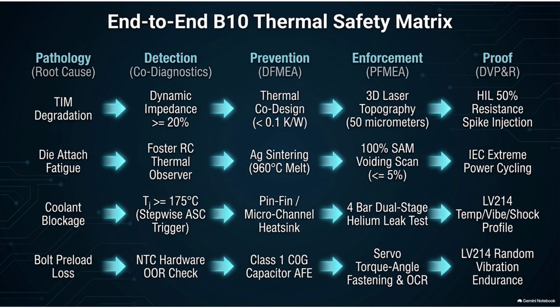It proves the physical architecture can withstand reality. It verifies that those tiny aluminum pin fins inside the cooler don't develop fatigue cracks and snap off under intense vibration. It proves the thermal paste doesn't wash out or pump out when the metal is shaking and warping. And the sensors? It ensures the delicate NTC temperature sensor's accuracy doesn't drift more than 1 degree Celsius, despite being violently shaken and frozen. And crucially, it guarantees the electrical insulation resistance remains rock solid above 100 megaohms, meaning the high-voltage electricity won't break through the insulators and short out to the chassis of the car, which could electrocute a passenger.